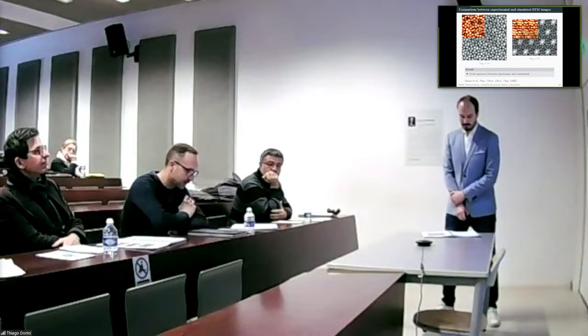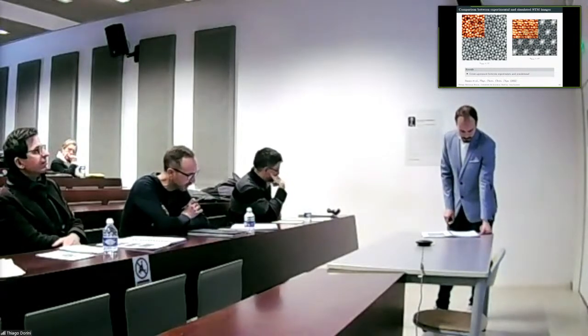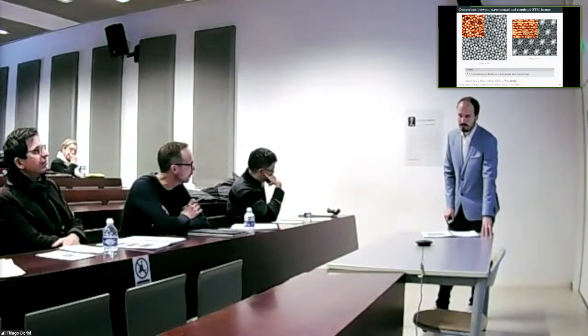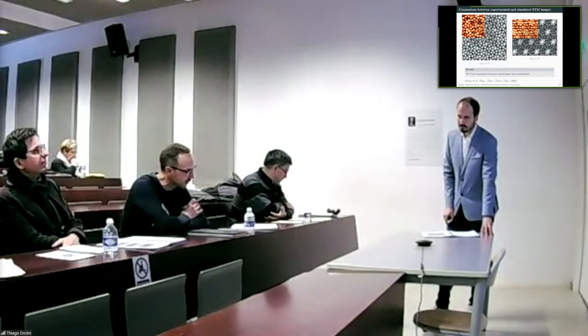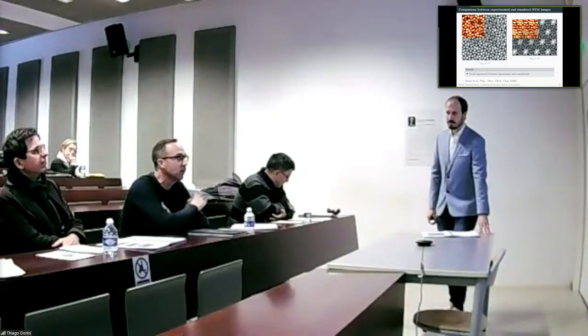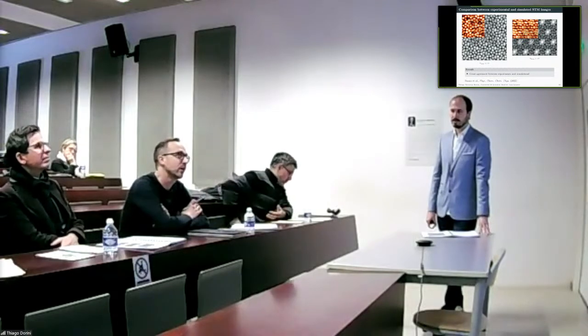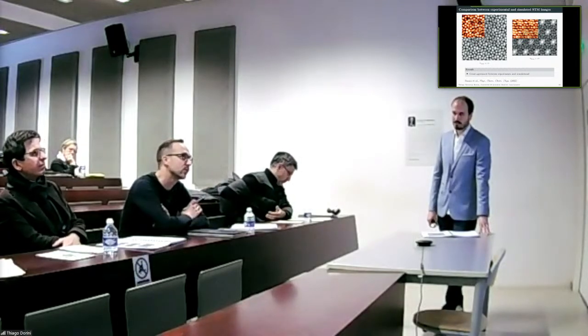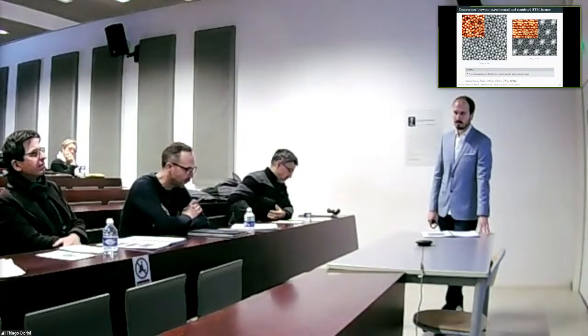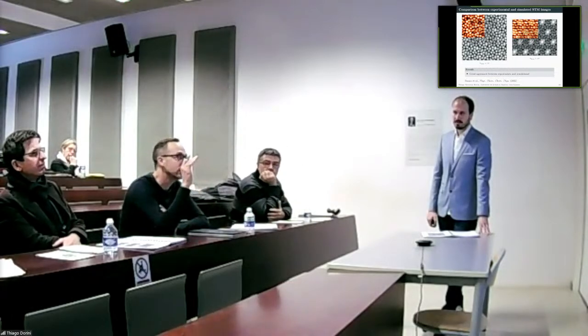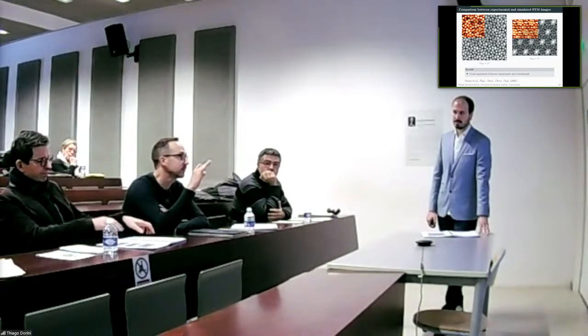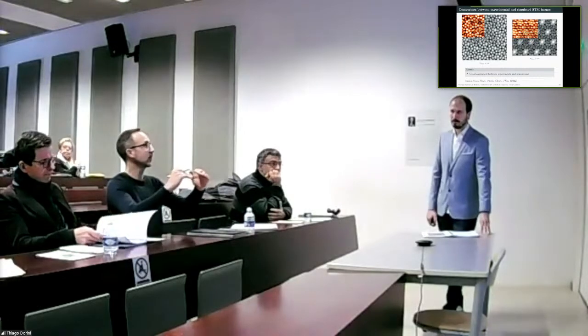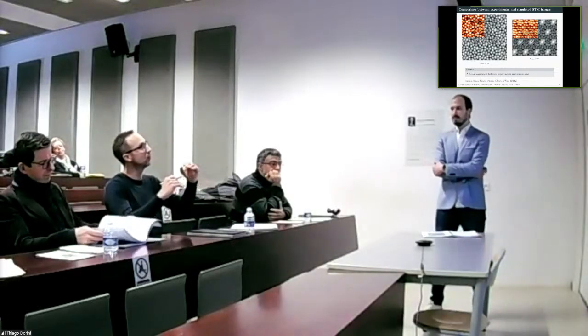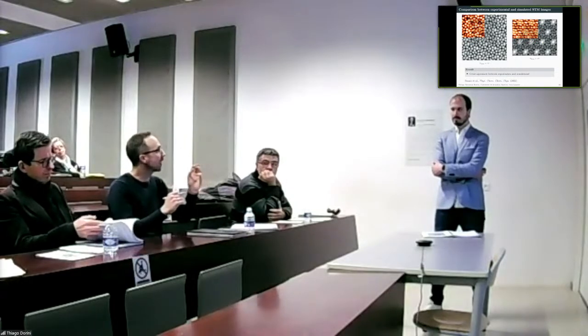What you show in the density of states calculation here is that titanium has the highest contribution over the whole energy range. Yes. And if I would do the integration from 0 to 1 or 0 to -1, I would have much more than a factor of 10 higher density of states coming from titanium. Now in the true system, you have only a height difference of 0.5 angstrom between the titanium height and the strontium height. So they're almost on the same level. That's why it's really surprising to me that you do not have significant signal coming also from the titanium.